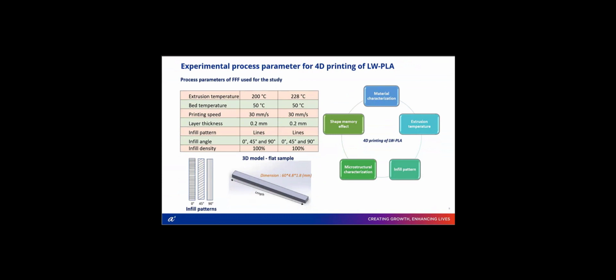With the initial characterization and experiments, we used two extrusion temperatures, 200 degrees Celsius and 228 degrees Celsius, with three different infill angles, 0, 45, and 90. We chose these process parameters to study the shape memory effect of lightweight PLA. Overall, the samples printed at 200 are unfoamed samples and the samples printed at 228 are foamed samples. To study the combination of process parameters, the extrusion temperature and the infill angles, we selected a flat sample and observed the microstructure of the flat sample and the shape memory effect.